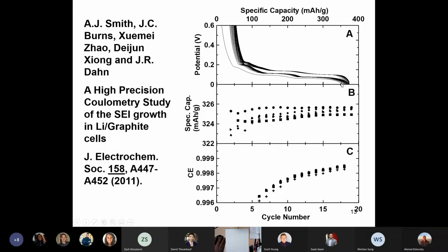Okay, so what this is telling you is that there's extra lithium being delivered during the lithiation that's being incorporated in the SEI. That's why the capacity gets bigger every cycle. And that lithium that's been delivered to the SEI cannot be removed. So there's 4 cells, maybe it's 5 cells being measured here in this experiment. And panel B plots their specific capacity versus cycle count. And like I'm telling you, the capacity that's being charged and discharged is constant, right? You can see it's to a very high degree of precision. There is no capacity loss happening to the graphite. The graphite can still accommodate just as much lithium as it could at the beginning on every cycle, but you're losing lithium to the SEI.